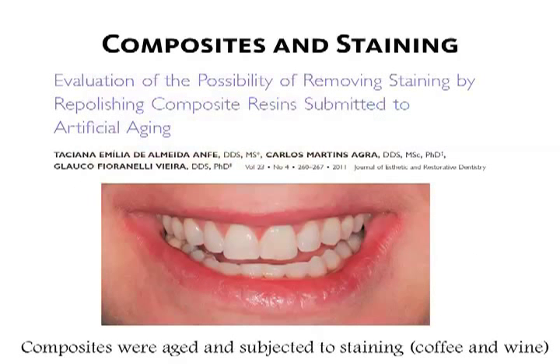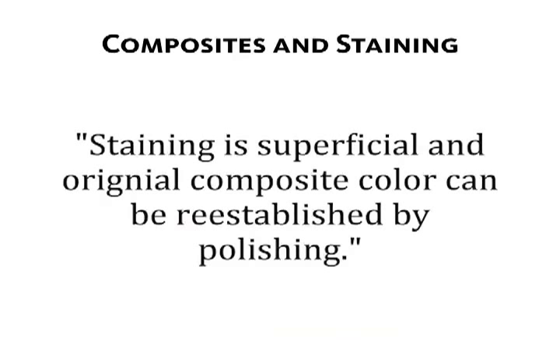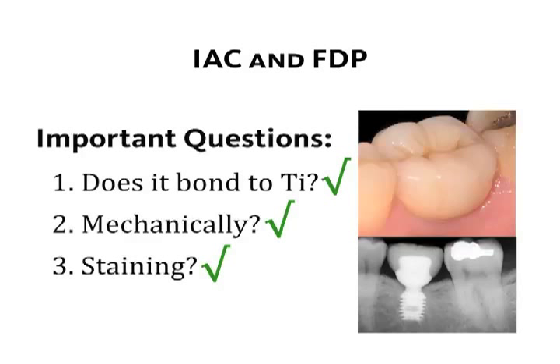For the last question, regarding staining, there's a recent study where several composites were aged and subjected to staining in coffee and wine. The authors found that staining is as superficial as 20 microns and that repolishing can reestablish the composite's original color. So, as we could conclude, the first question, bonding to composites, does not seem to be an issue. The reliability of IACs and bridges seems to match that of metal ceramics. And third, should staining be an issue, the possibility of reestablishing the composite's color by repolishing has been shown to be effective. In addition, composites in general are very user-friendly as they can always be added chairside.